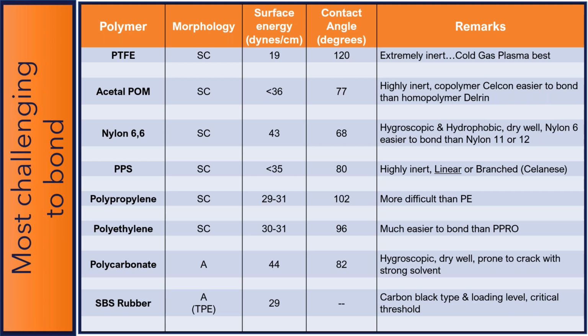I'm mentioning polycarbonate, and it really shouldn't be on the top 10 list here because it's not all that difficult to bond. But sometimes companies do have problems with it. It is an amorphous plastic, but it's generally more difficult to bond just because it's hygroscopic and it's very prone to cracking if a strong solvent is used. So I just wanted to briefly mention polycarbonate.